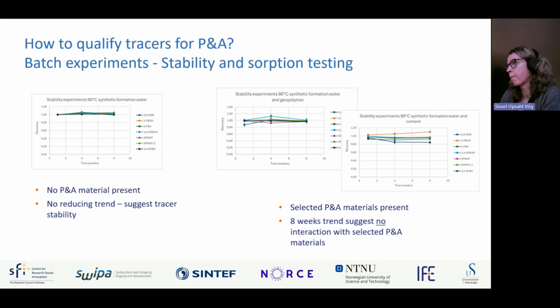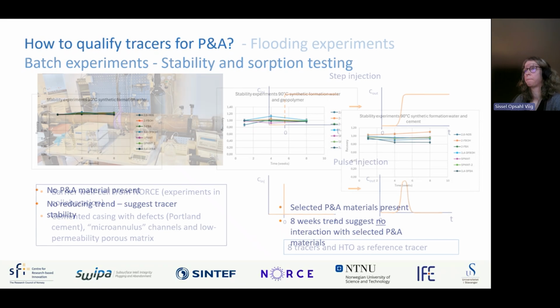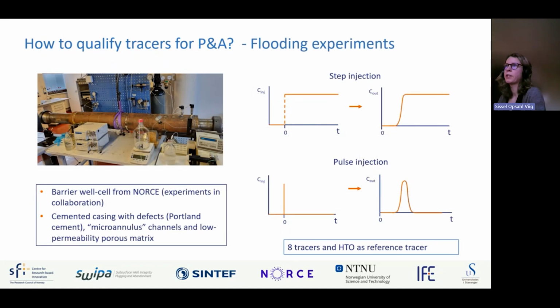On the right-hand side, we see results from some of the experiments where we have introduced plugging materials. Here we see results for tracers exposed to 90 degrees Celsius with geopolymer present. And here we see results for tracers exposed to 90 degrees Celsius with cement class G present. And again, we see the exposure time on the x-axis and the recovery on the y-axis. If you look at these two figures, we have some spread in the results, but we don't see any reduction in the tracer concentrations after 8 weeks. And this indicates that we don't have any interaction between the selected plugging materials and the tracers included in the test. That was the results we have so far from batch experiments.